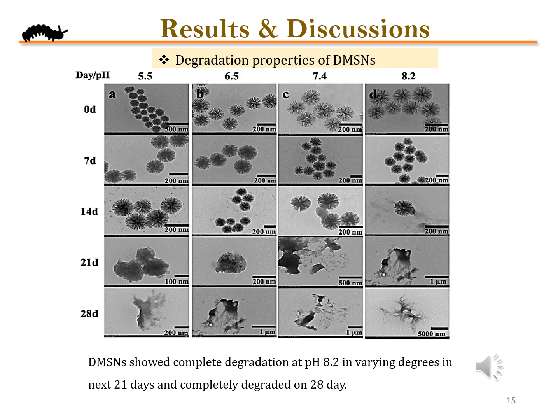Later, it is very necessary for a nanoparticle to show minimum side effects and less toxicity. Hence, it is necessary to see the degradation properties of DMSNs, and it was seen that as the material was kept in different pH solutions for several days, the DMSNs completely degrade at pH 8.2 in 28 days.